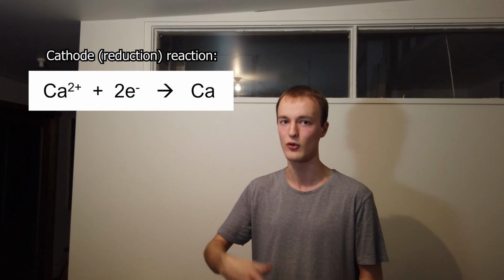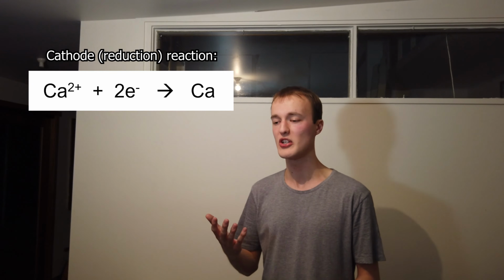There are a couple of ways we can try to get around the calcium solubility problem in the calcium chloride melt. First option is to use an extremely high current density on the cathode. The cathode is, of course, where we generate the calcium by the reduction of calcium ions. We give electrons to calcium ions to form calcium metal. And if we keep the current density on the cathode high enough, we might be able to generate calcium faster than it dissolves back into the melt. It's unlikely because most references say that this needs to be done in an inert atmosphere in order to get it to work properly, but we are going to have a go.